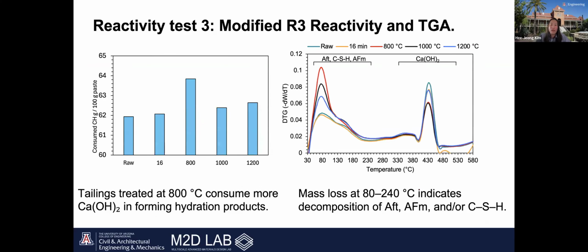To further confirm the reactivity of the activated tailings, we performed the R3 reactivity test and the TG-DTA. And these tests help us to see how much CH was consumed during the hydration. And this shows whether the tailings actually participated in the reaction. The result shows that the 800 Celsius activated tailings, which had the highest compressive strength, also consumed more calcium hydroxide. And this means that they are more reactive, and this result is clearly supported by TG-DTA data. The TG-DTA curves also suggest the formation of hydration products such as ettringite, monosulfate, and CSH, which confirm the real cementitious reaction happened.